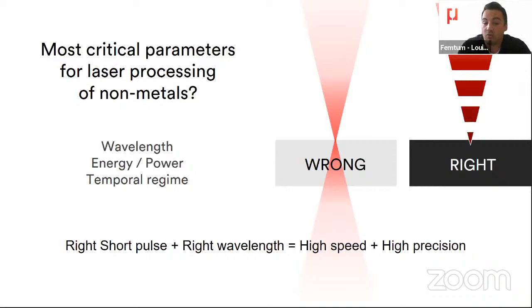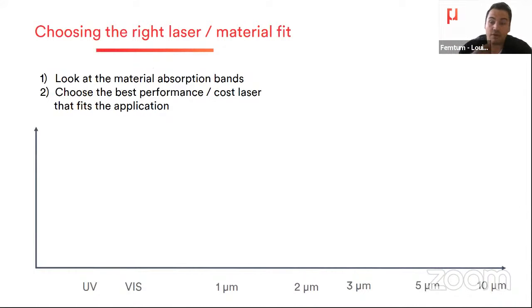And when you are also at the right wavelength, what happens basically is if your material is transparent, it will just transmit the light through. It will not be absorbed by the material. So what you need is a material that is opaque to the laser wavelength. Having all this in mind, if you have an application with a material and you're about to choose the right laser to do the job, then first thing first, look at the material absorption band, especially if it's a transparent, organic, or delicate material, and then choose the best performance to cost laser that fits your application.